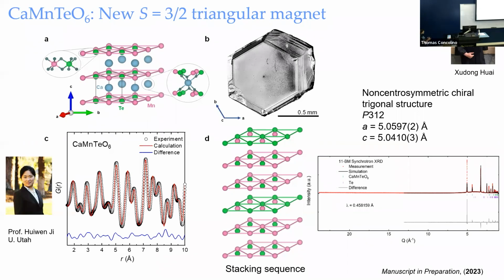Okay. So now if you look at the habit of the crystal, you see that we are actually onto something, but we have some trouble here. So this material crystallized in a noncentrosymmetric trigonal structure, space group P312. So you can look at the symmetry and you say, okay, there's no systematic absence here. So how can you tell that you are actually looking at the correct space group? So we verified with not only single crystal diffraction, powder, 11-BM synchrotron X-ray, and later we also verified with PDF and neutron. So this is the space group that allows us to describe the structure with the least disorder and the highest symmetry.